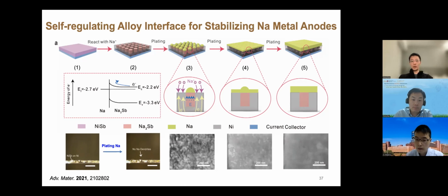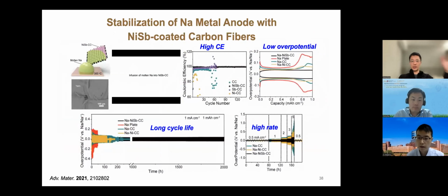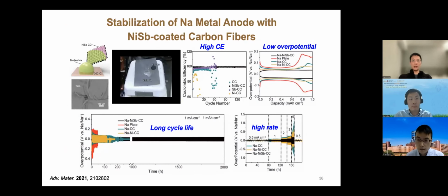Then we just use whatever I told you in the previous slides, and by wicking this onto a three-dimensional structure, we can make a sodium metal composite anode, right? And what we observe is exactly the same as what we observe in the lithium case. It's highly flexible, even though we don't really use it for flexibility application. It has a much improved Coulombic efficiency. It has a very low overpotential during plating and stripping. The cycle stability is way higher, and at high rate it still performs similarly.